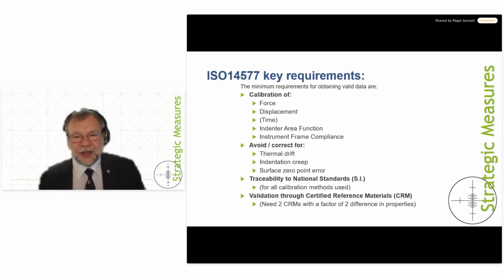I always have to say this because ISO 14577 is the instrumented indentation standard. It allows you to measure a whole range of things, but in order to do that with reproducibility and accuracy, you need to be able to do the correct SI traceable calibrations. So you need to calibrate force, you need to calibrate displacement. Increasingly, as we start looking at dynamic indentation and creep rate measurements, we are starting to have to measure and calibrate time in an absolute way. And of course, we need to do the indenter area function.